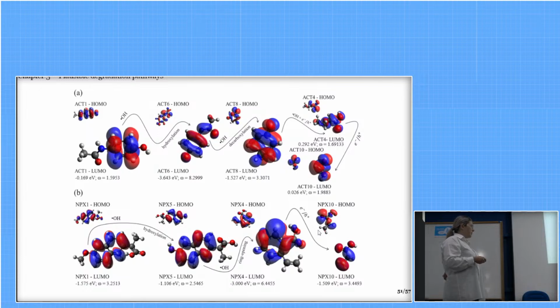And for naproxen, similar pathways, so first hydroxylation caused by the formation of hydroxyl radical, then ring opening reactions, and the final mineralization through the electronic charge transfer phenomenon.